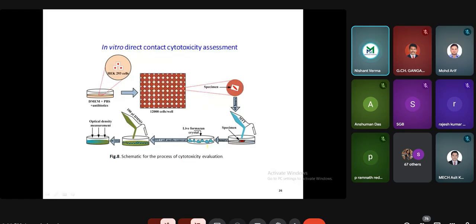So we have done the direct contact assessment test in collaboration with another lab, because as you already know, I am from a mechanical background, and I am not much aware of these cell-related things, but something that I have learned. Firstly, we prepared Dulbecco's modified Eagle medium with phosphate buffered saline solution. We supplemented the cells with bovine serum, so that cells should not be killed by a deficiency of nutrients. The basic point is that cells can be killed by contact with the material, but they should not be killed by a deficiency of nutrients.